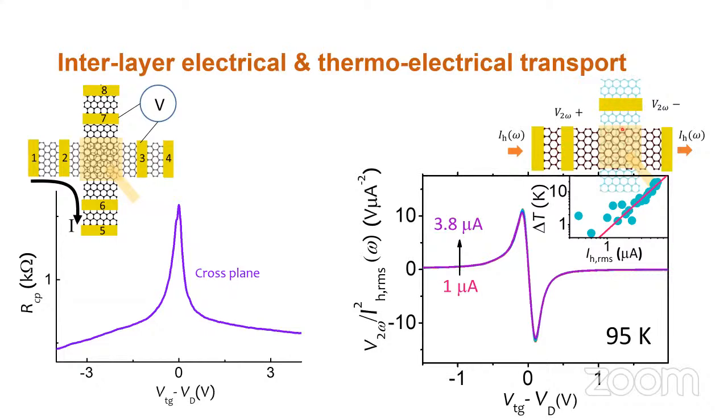Okay. What is interesting, and I want you to take a note of this, is that by increasing the heating current, we can see the temperature difference between the two layers is increasing, and you can actually maintain a temperature difference of nearly 30 Kelvin or even more, 30 to 40 Kelvin between two layers of graphene that are separated by 0.5 nanometer, which is actually a staggeringly large temperature difference if you think about it, between two systems which are so close physically. So which actually is a very interesting observation in itself.